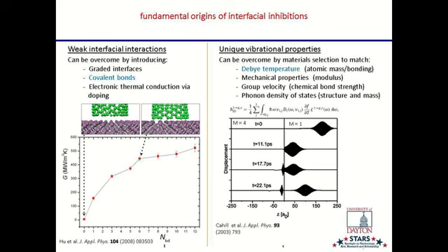This is simulation work: if you could magically make covalent bonds between this carbon nanotube up here and whatever other more ordinary engineering material you had it in contact with, and control the number of those bonds, you could increase, this is the inverse of interface resistance, this is interface conductance, so bigger numbers are better. The more covalent bonds you have, like down here, this is the number of covalent bonds, the more of those bonds you have, the higher that conductance is, the better heat propagates from one surface into the other.